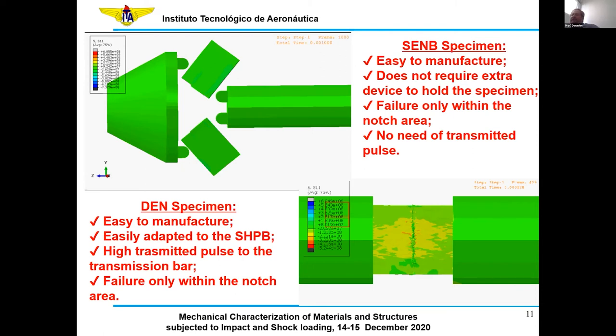For the DEN specimen, which is the double edge notched, again, it is a very easy specimen to manufacture, even easier than the SENB. It can be easily adapted in a direct way to the split Hopkinson pressure bar. It also ensures a very high transmitted pulse. And if well designed again, we ensure that failure occurs only within the notch area.